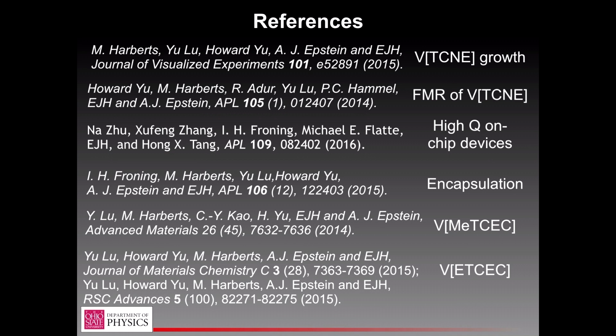Art Epstein tried some electronic gating and didn't see anything, but I wasn't part of those experiments. I'm not sure how that was done and whether that's really a no. Some solid electrolyte gating to really gate the heck out of it might be interesting if we can come up with a way of doing that without melting the material. Not only that, but this solvent issue: if they're sensitive to polar solvents, then depositing the electrolyte is a challenge.